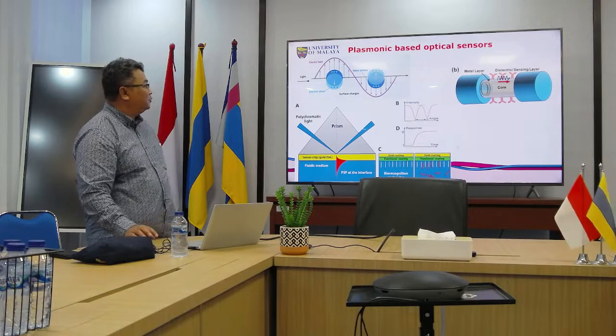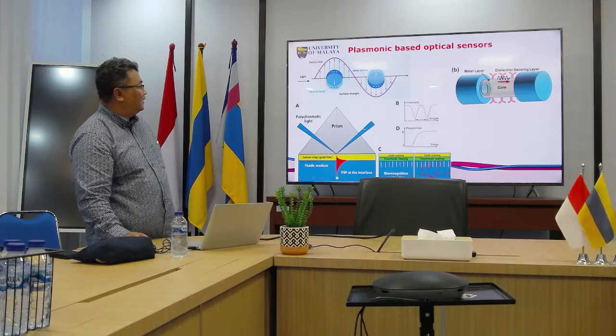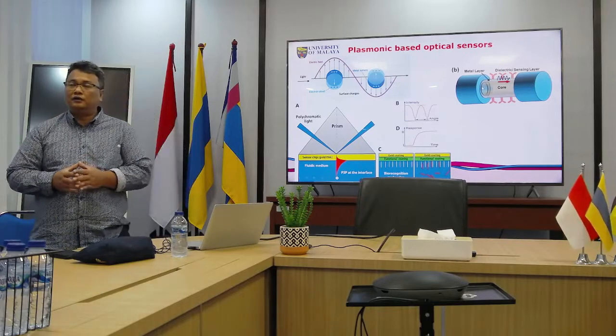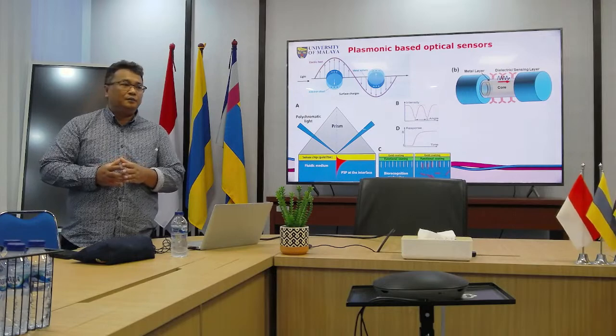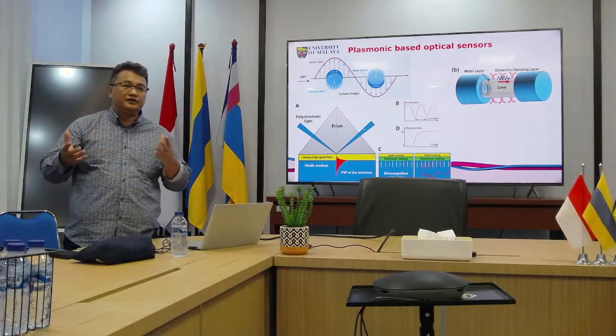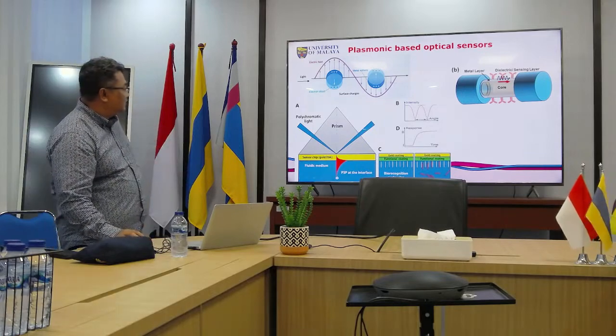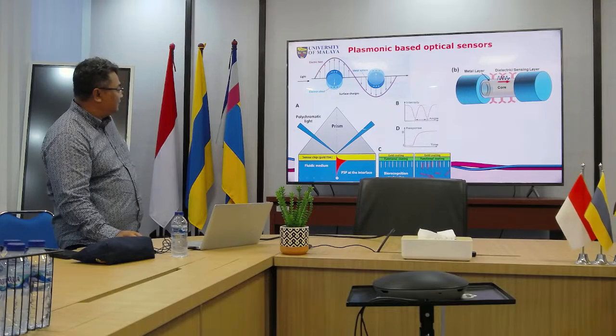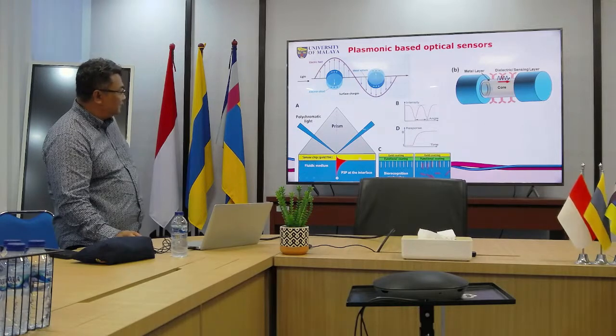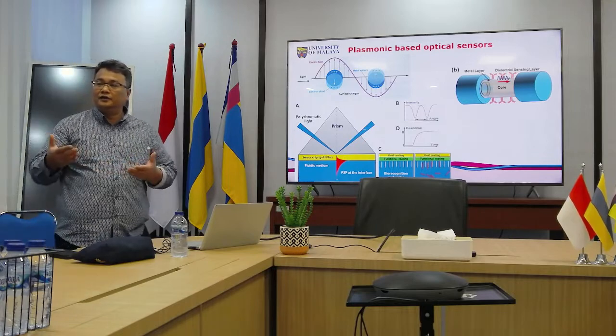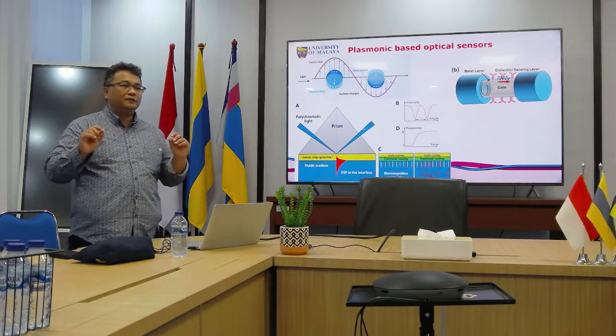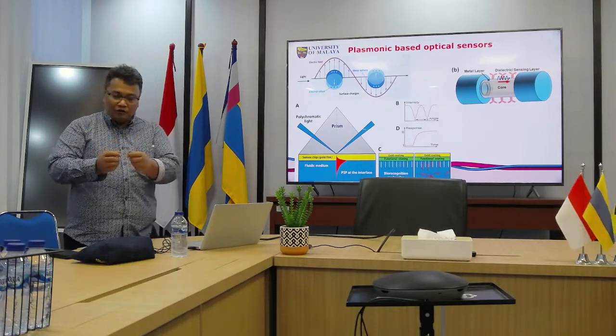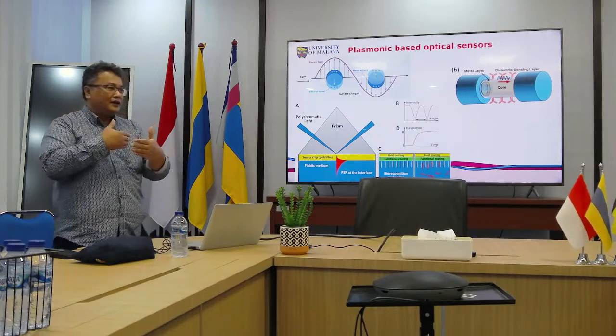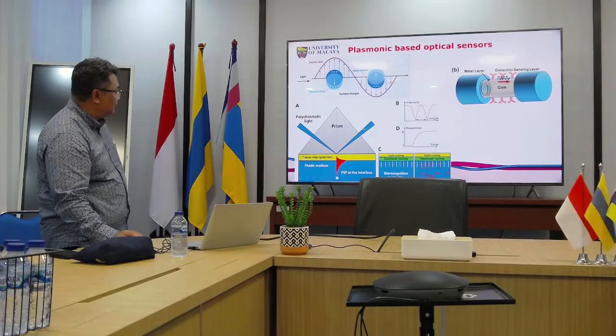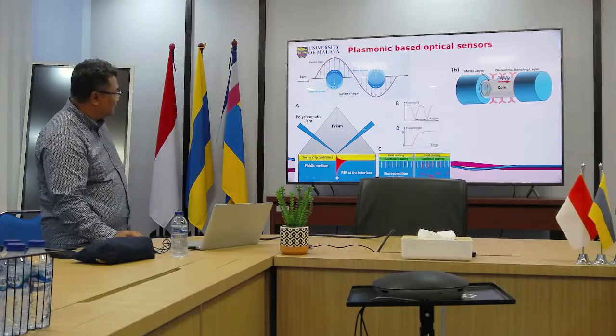Okay, this plasmonic: you put some metal, and the interaction between electrons and photons can produce plasmonic oscillations. Normally people use a prism. When you shoot light here, you get this evanescent field. If you have a gold layer here, a metal layer, it must be thin, 40 to 50 nanometers. At 50 nanometers the gold is actually transparent. You coat it there, I think this professor is doing this plasmonic work in the lab.